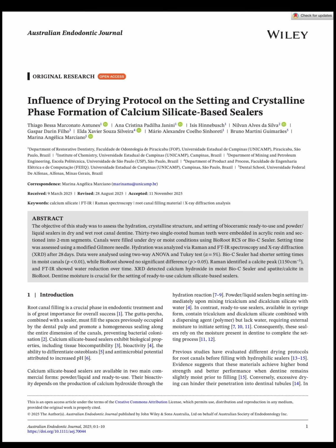So for the conclusion, dentin moisture is essential for the proper hydration and setting of ready-to-use bioceramic sealers. For clinical practice, they recommended that root canals should be kept slightly moist rather than completely dry when using materials like BioC sealer to ensure optimal setting and the formation of calcium hydroxide.